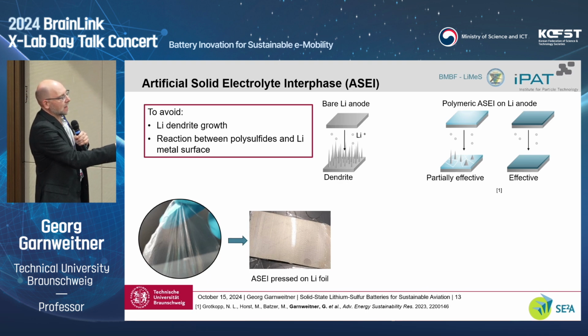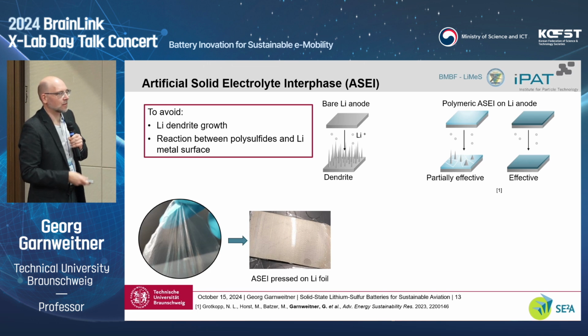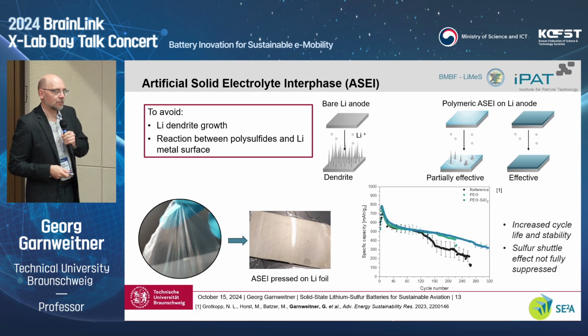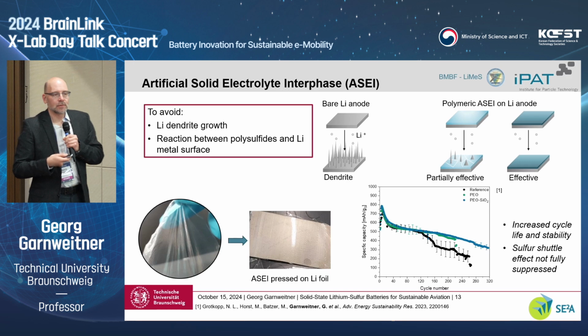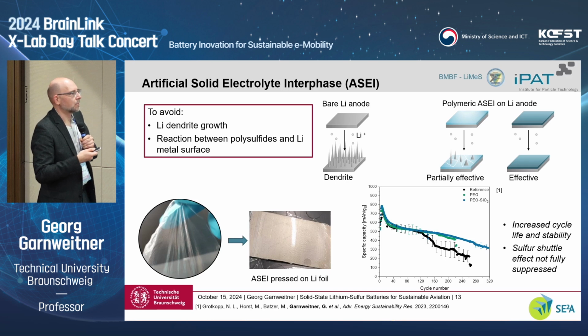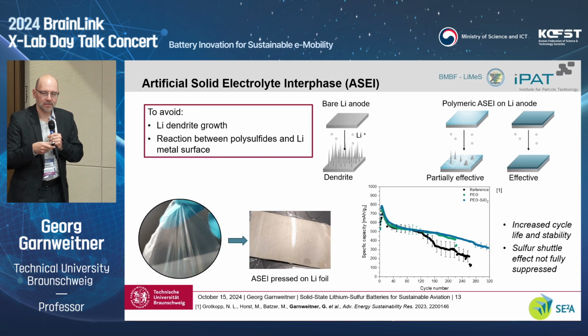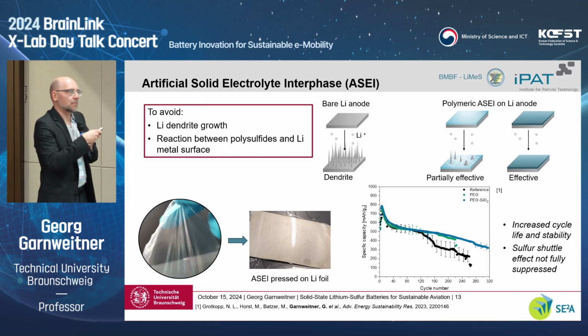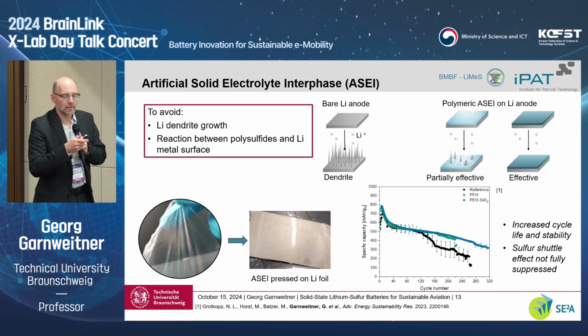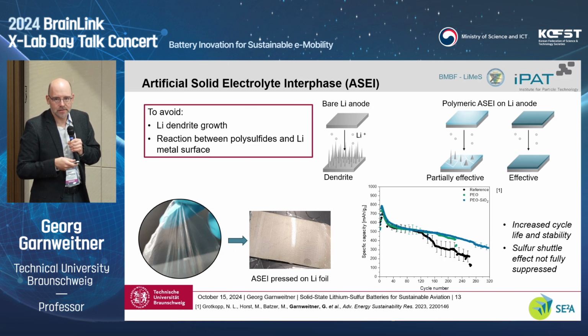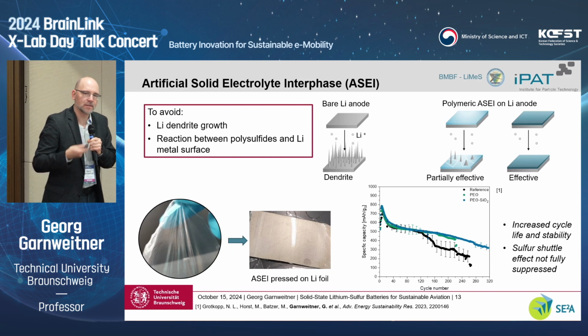And in this case, we had a foil that is conductive to lithium ions that was simply pressed on the lithium foil. That gave a much more stable and much more reproducible performance of the batteries that we tested. Nevertheless, we still see some decrease over hundreds of cycles, which means that we still have some of this polysulfide